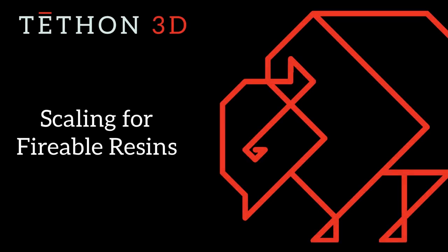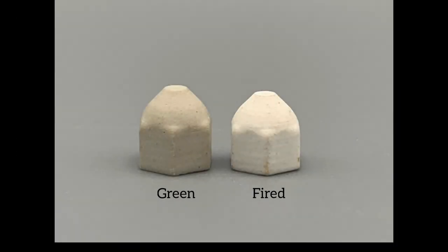At Tethon3D, we sell a variety of materials which are capable of going from a green state or pre-fired to a bisque state or fired when heated in a kiln or oven. When going through this process, the print will shrink, and this amount can be anywhere between 4 and 17%.